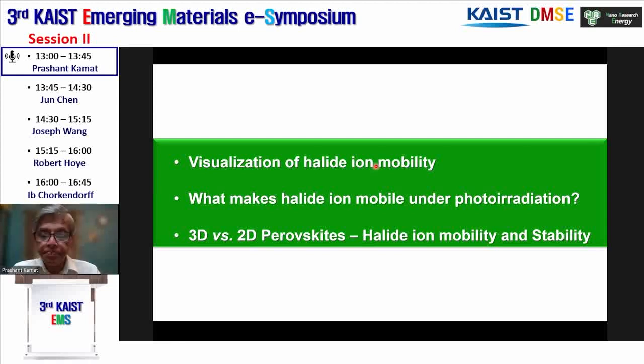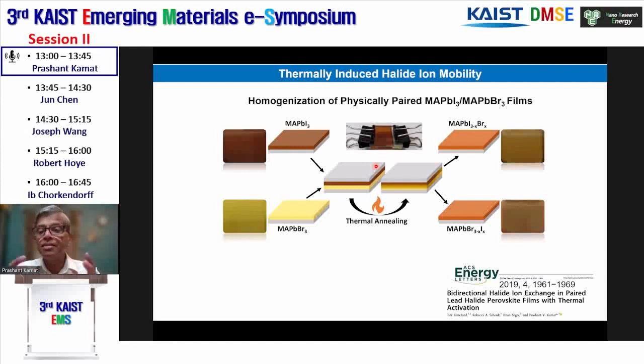And the last one is 3D versus 2D perovskites, and some of the new results that come out from our lab. Okay, first, how we can see this halide ion mobility. It's a very simple experiment. You put films of methyl ammonium lead iodide and methyl ammonium lead bromide on two different glass slides, and just put them together in a sandwich fashion, clamp them, and put it on a hot plate.